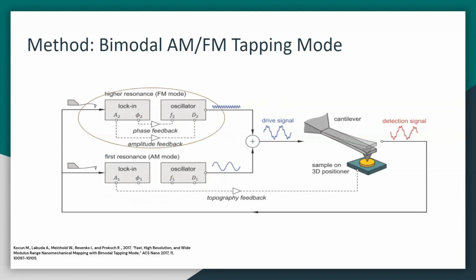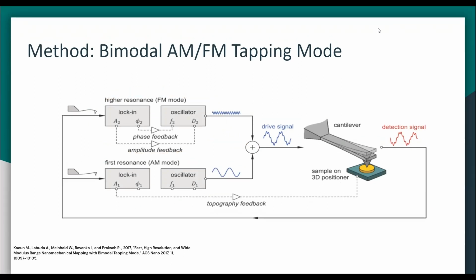But simultaneously, the higher resonance FM mode is driven with A2 amplitude as seen in the figure, and then the phase and amplitude feedback loop maintain constant oscillation while the sample is being scanned. So as a result, we're getting two feedback results at the same time, topography and the Young's modulus. To summarize, the first mode provides information on the topography, amplitude, and the loss tangent or phase, and the second mode info is about the stiffness or modulus from the frequency shift or energy dissipation, which also relates to the amplitude.